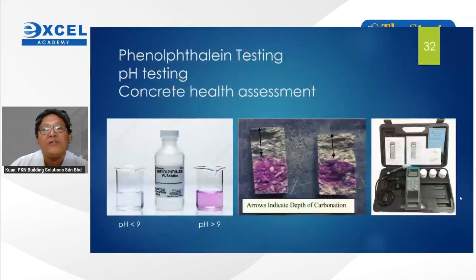Okay, and carbonation is one of the keys to concrete deterioration, and it can be identified using phenolphthalein solution, whereby if the carbonation has entered into the concrete, it will neutralize the concrete. By neutralizing and bringing down the pH of concrete, when the concrete pH reaches 9, corrosion will start on the reinforcement steel bar. So we actually need to know the depth of carbon dioxide penetration in order to understand whether the infiltration of carbon dioxide gas or carbonic acid has triggered the corrosion. This can be done easily using phenolphthalein solution.